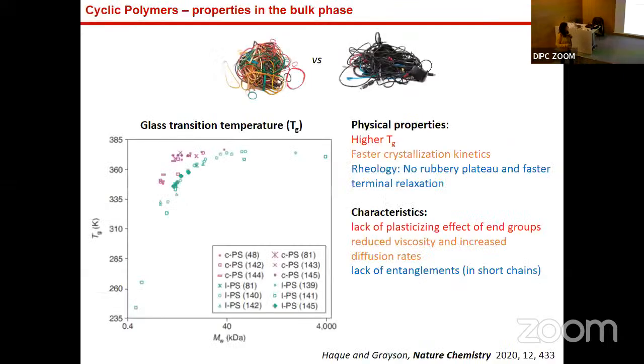So let's go to the properties. This is a typical physical property that we observe in cyclic polymers, which is the glass transition temperature. Cyclic polymers in the low molecular weight range present higher glass transition temperatures than the linear ones. Then at high molecular weight, they all go to the same temperature, which is called the infinite glass transition temperature. This is due to the lack of plasticizing effect of end groups on the mobility of these polymer chains in the low molecular weight range. The longer the molecular chain, the more these end groups are diluted,